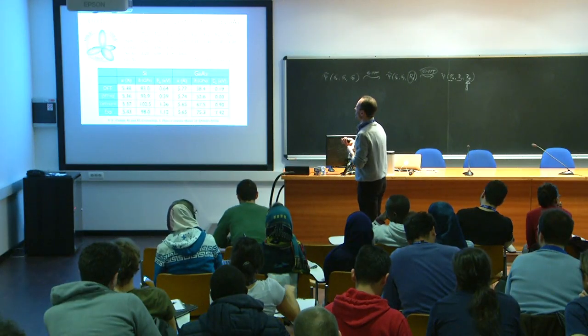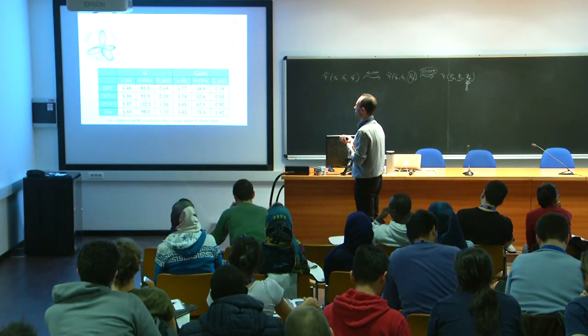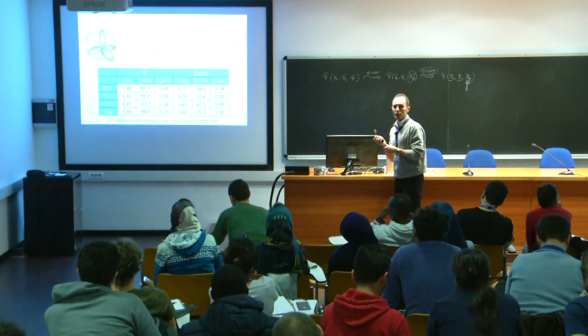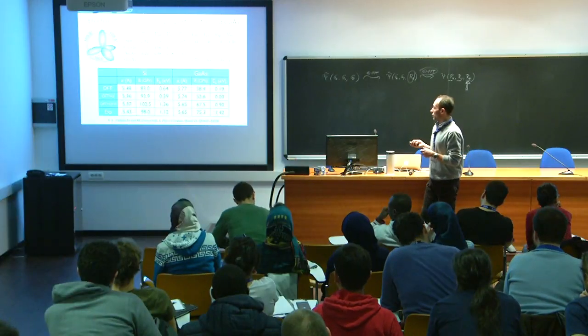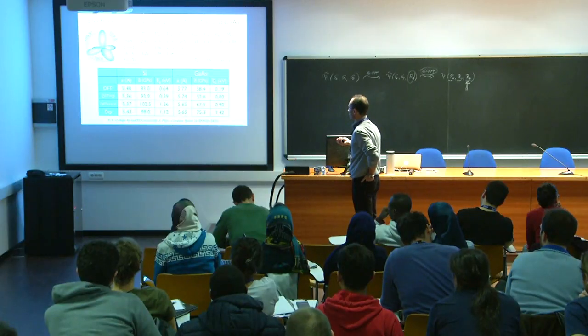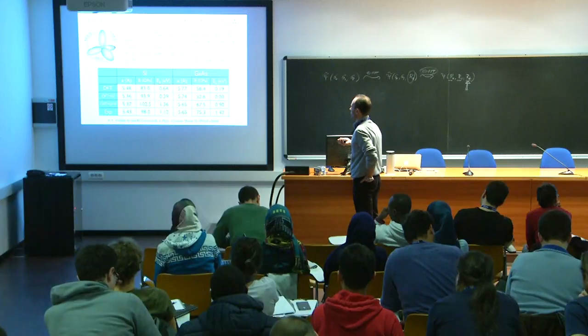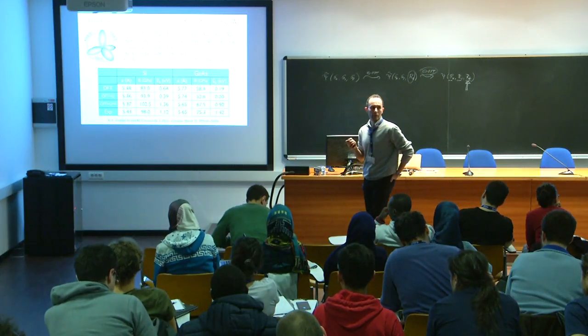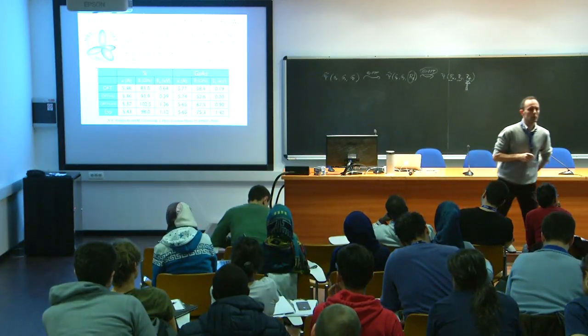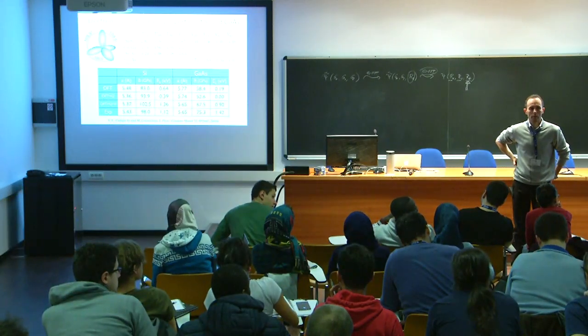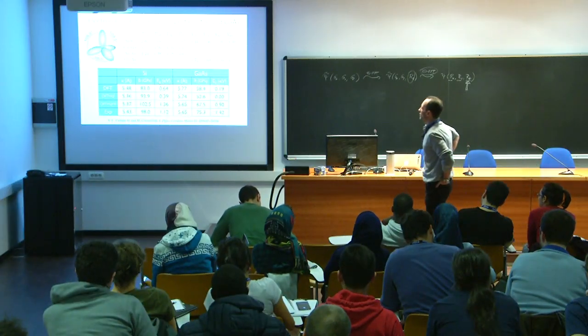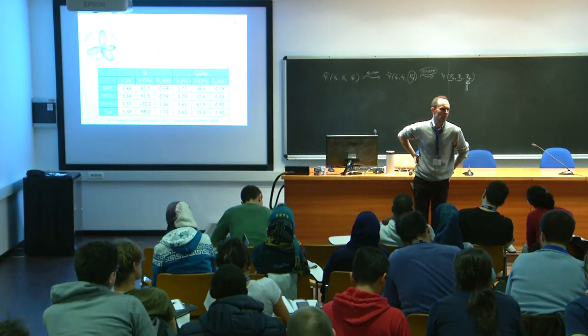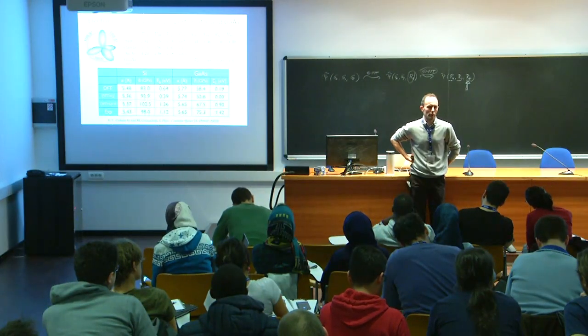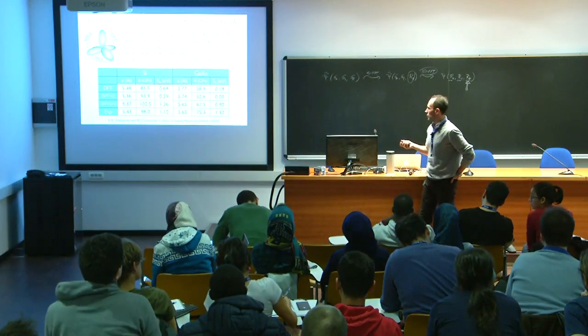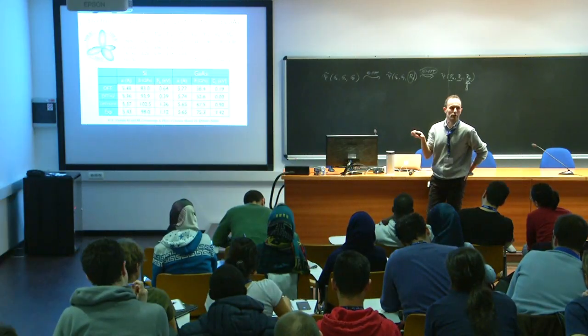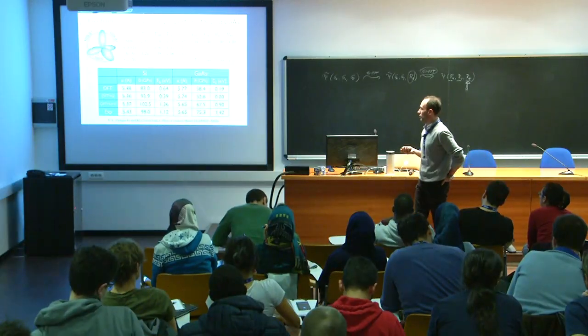So again, this is not in perfect agreement with the experiment, but at least we correct the result in the right way. Okay, and that's true also for gallium arsenide, and in most cases you get a significant improvement also of the equilibrium lattice parameter and bulk modulus. Yes, yeah. I don't remember if self-consistently or from a one-shot calculation from the ground state. This detail is in this paper. I think it was self-consistent, but I'm not 100% sure.